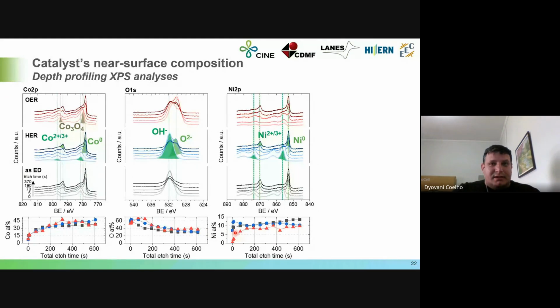And for nickel, we have a slightly different behavior of the nickel concentration on the surface and underneath the surface. For oxygen evolution reaction, we almost don't have nickel, just a little nickel on the surface. But for hydrogen evolution reaction, the nickel on the surface is more or less the same as as-electrodeposited. So negative polarization of the catalyst just protects against nickel dissolution. But for oxygen evolution reaction, the nickel is dissolved during the oxygen evolution reaction, and not during the open circuit potential. So the cobalt is dissolved since the open circuit potential step, since the first step, but the nickel is dissolved just during the oxygen evolution reaction.